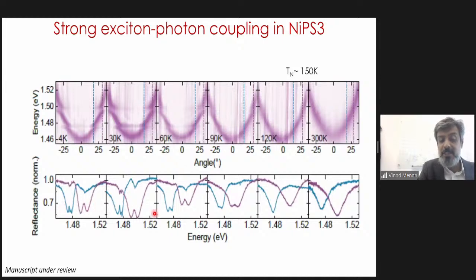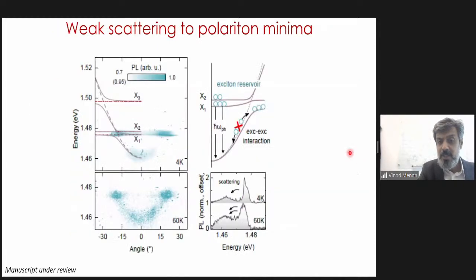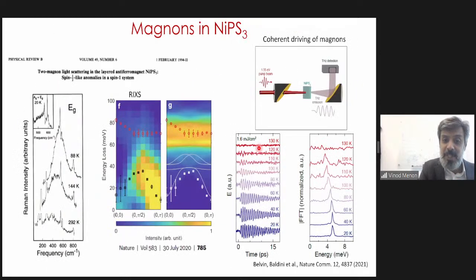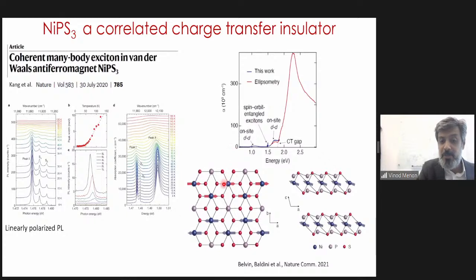The other interesting thing is, as I increase the temperature and go past what is called the Néel temperature, where antiferromagnetism disappears, then this whole strong coupling and the excitons and everything disappears as well. We studied the nonlinear response of this material, and we see that it's not easy for these polaritons in this system to interact. So what this told us is that these excitons are probably tightly bound, but they have a very weak oscillator strength. And the only explanation we can come up with is that you have the electron sitting on one of these nickel atoms, and the hole is sitting on one of these sulfur atoms, or it's shared between two sulfur atoms. At least there are two options there in the two sulfur atoms.